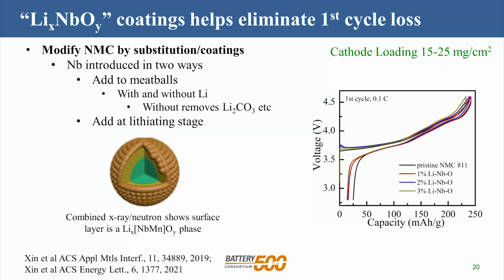So we added the niobium to the meatballs, just put a solution there, soaked it, then we fired it to get it to either coat the material, or we went to higher temperature, it would substitute totally in lattice. And I show you a schematic of those meatballs. It turns out when the niobium atom goes into the lattice, it kicks out a manganese, so the actual surface coating is a mixed lithium niobium manganese oxide. It's not just niobium.